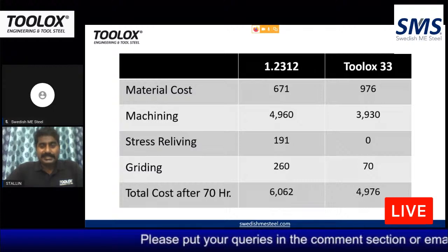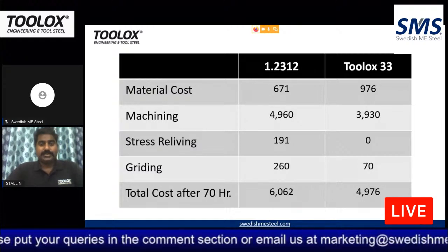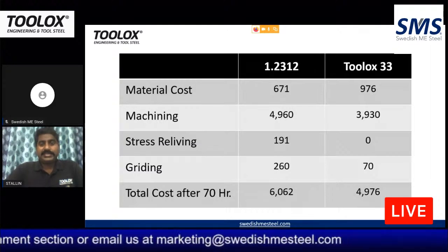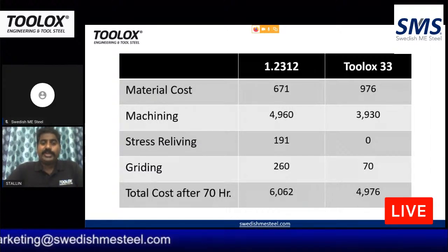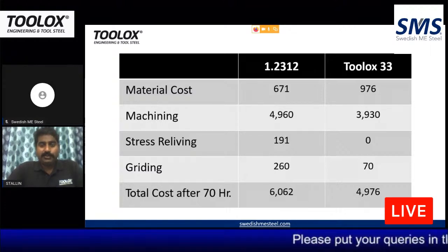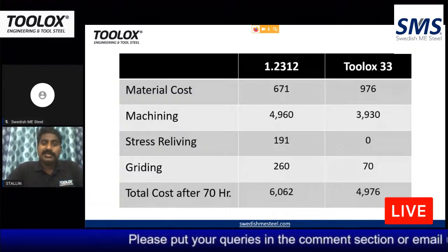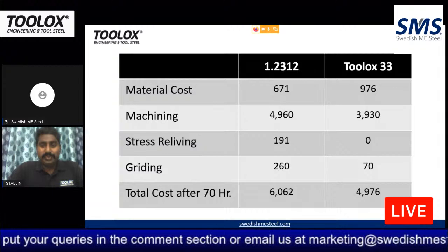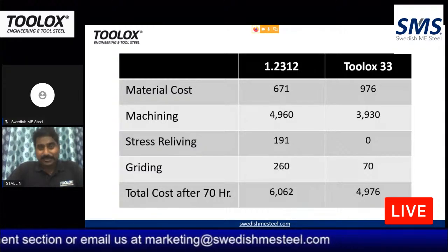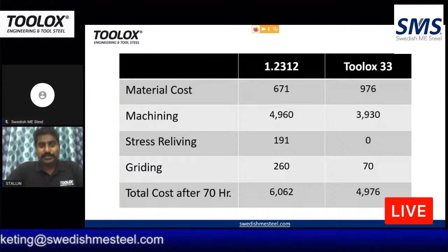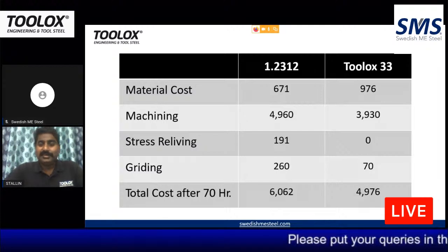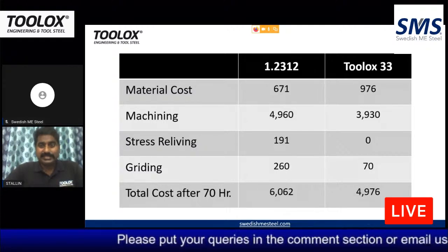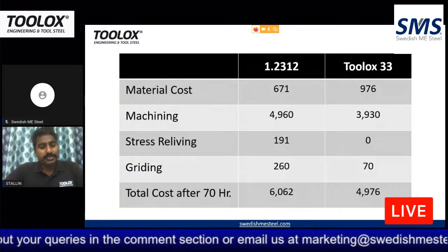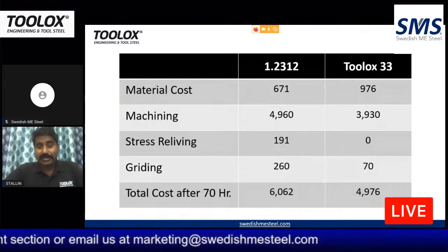And Toolox is internally stress relieved. There is no internal stress involved in Toolox, which means that even after extensive machining, you need not do any stress relieving for the material. This is how it happens, right? You do a bigger mold, you do complex machining. You either do the stress relieving or you keep the mold idle for 1 or 2 days. That's also time and that's also money that you incur. With Toolox, it's not required for you to wait for so many days. As soon as you finish your machining, you can go on to complete your next task with the material. No problem. No stress relieving in the material. That's an added benefit for you.